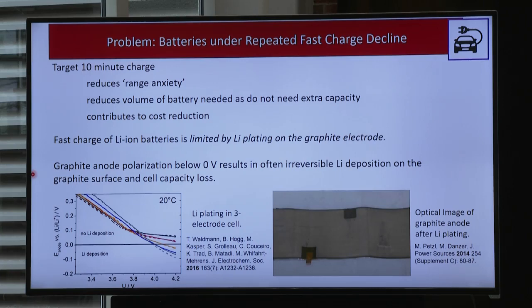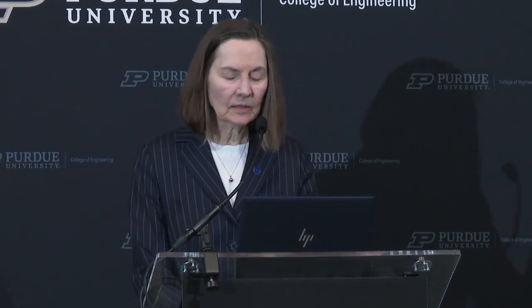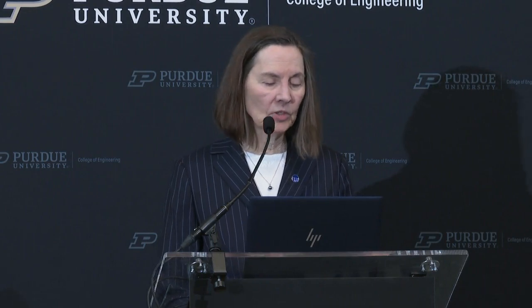And it turns out that in a lithium-ion battery, the problem limiting fast charge is that the graphite anode should accept lithium ions, where the ions move back and forth between the anode and the cathode. But instead, if you try to charge too fast, you drive the potential of the negative electrode below the potential of lithium, and you end up plating lithium all over the place. And when you plate lithium, sometimes that lithium becomes ineffective, and basically the batteries lose capacity and decline pretty fast if you do repeated fast charge.